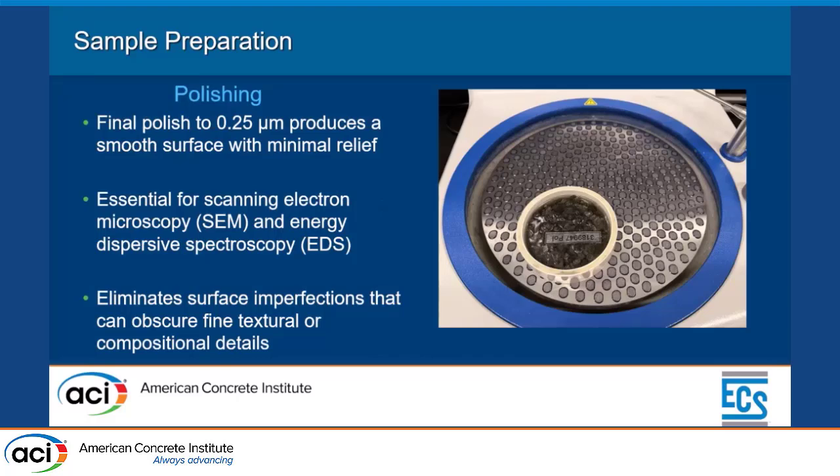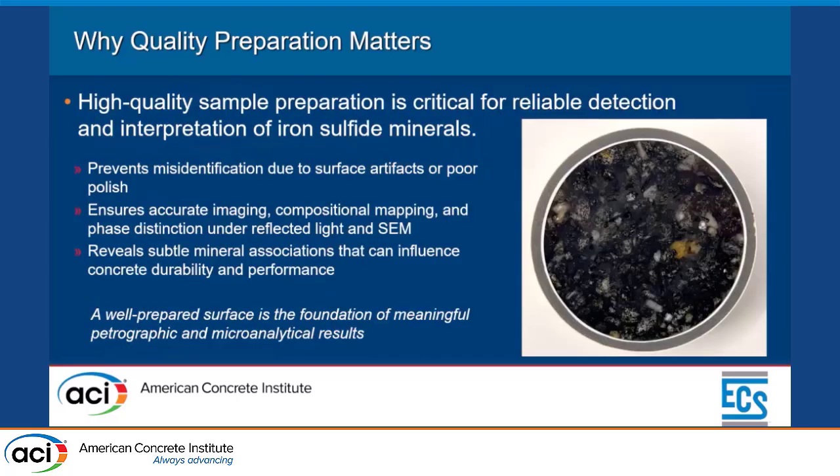So finally, we want to polish this to a real fine surface. We'll start with a diamond suspension spray on the steel and copper polishing discs, and move to really fine fabric pads for the final steps. It's really important to get reproducible, repetitive, and consistent motions when you're doing the polishing, so that we get a good surface for evaluation.